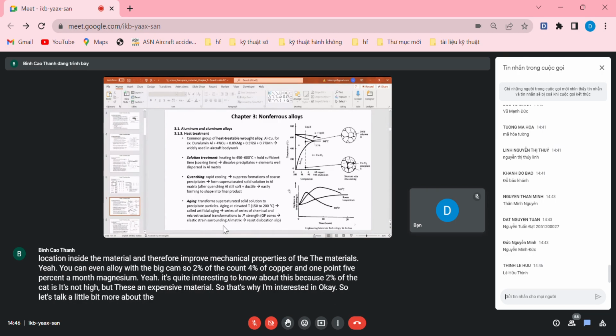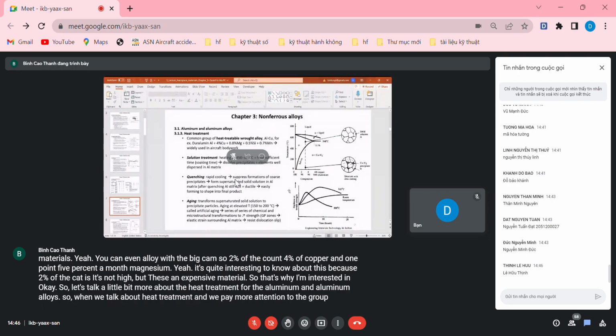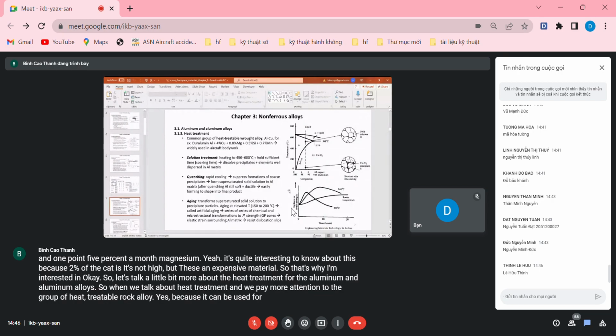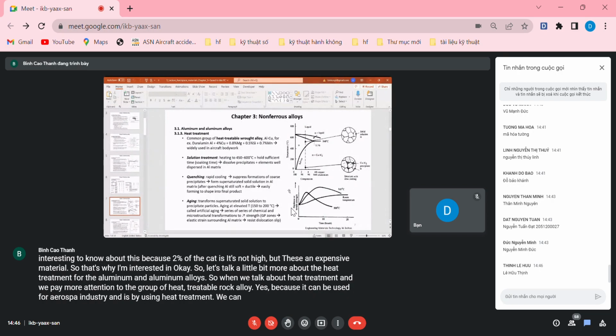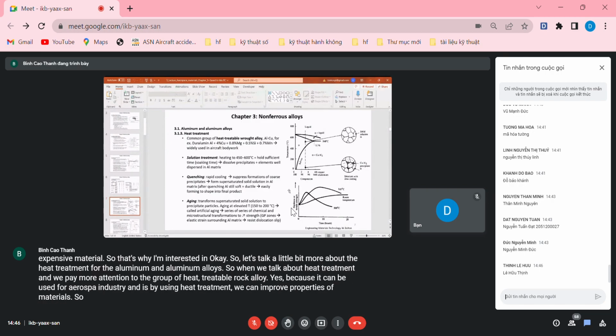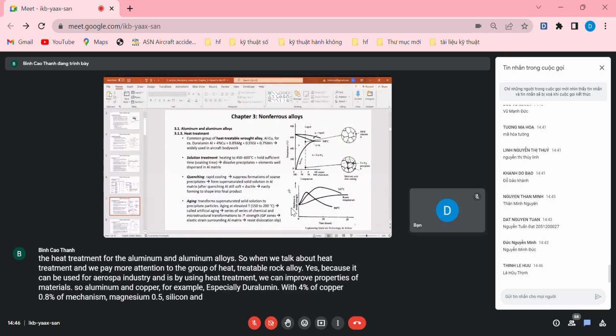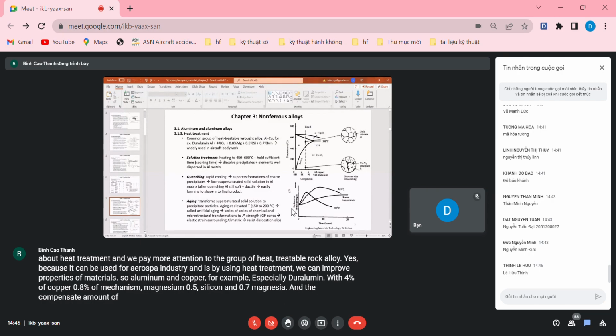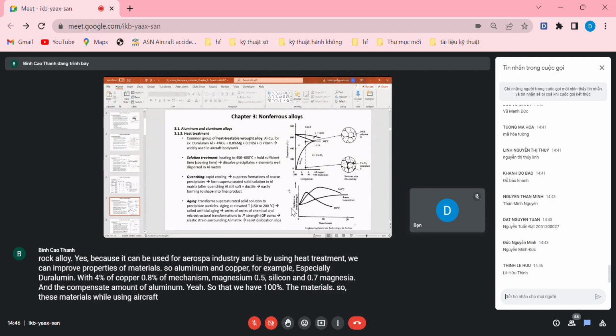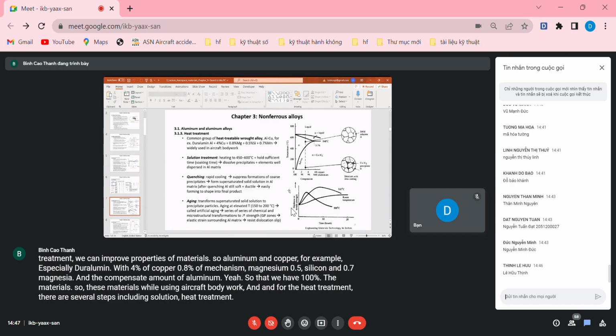So let's talk a little bit more about the heat treatment for aluminum and aluminum alloys. When we talk about heat treatment, we pay more attention to the group of heat treatable wrought alloys, because they can be used for the aerospace industry, and by using heat treatment we can improve the properties of those materials. So aluminum and copper, for example, especially duralumin with 4% of copper, 0.8% of magnesium, 0.5% of silicon, and 0.7% manganese, and the balance of aluminum, so that we have 100% by weight. This material is widely used in aircraft bodywork, and for the heat treatment, there are several steps, including solution heat treatment, quenching, and aging.